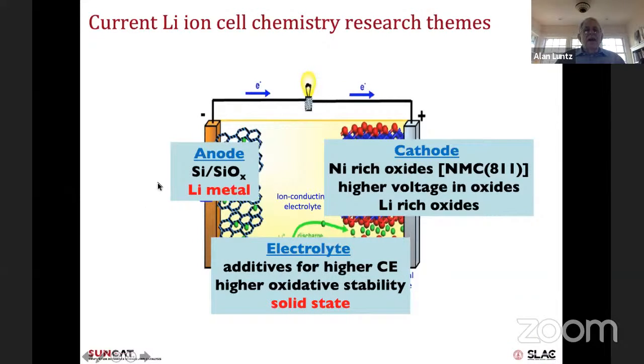So I just want to give a kind of general overview of what some of the important research themes are right now in the cell chemistry. I'll talk about a couple of them in more detail here. They're in red. On the anode side, there's a lot of work going on in silicon and silicon monoxide, SiO, adding that to the graphite or using them by themselves. The reason is their capacity for uptake of lithium is about an order of magnitude higher than graphite. So you can make a much higher capacity anode with these materials.